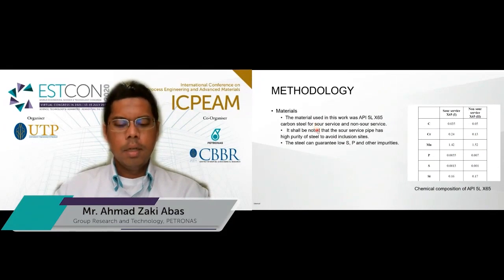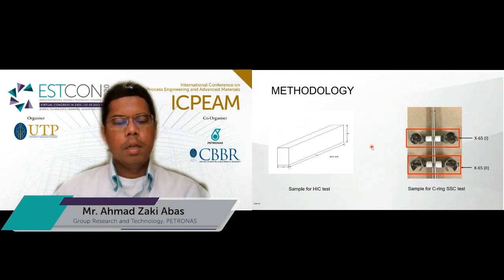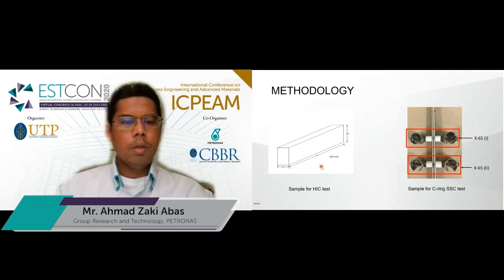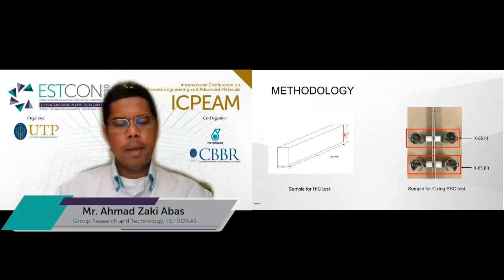Methodology. The material used in this work was API 5L X65 carbon steel, sour service and non-sour service. It should be noted that the sour service steel has high purity to avoid inclusions. The steel guarantees low sulfur, phosphorus, and other impurities. For the HIC test, the sample size is about 10 centimeters in length, 2 centimeters in width, and about 3 centimeters in height.